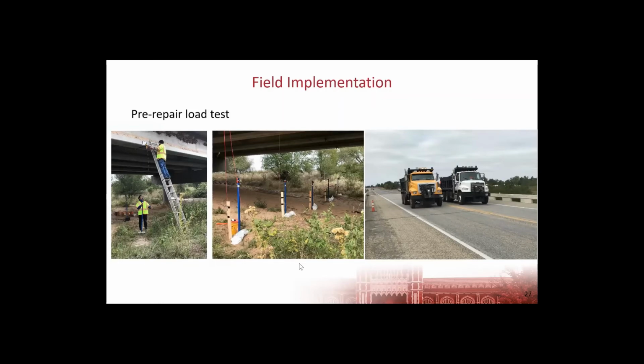We measured deflection on span 4, which was the continuous span closest to the north side, using laser distance measurements and then plumb bobs. We loaded it with 2 fully loaded dump trucks because the spans were pretty short. If we put a larger truck on there, we wouldn't get the kind of deflection effects that we were looking for.